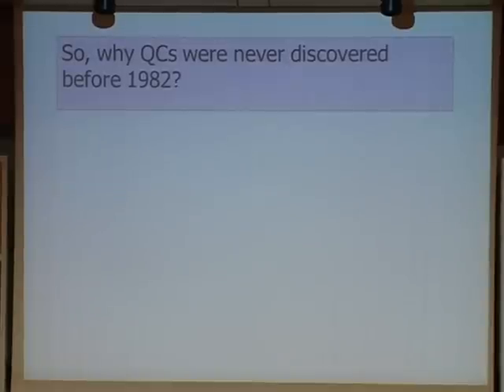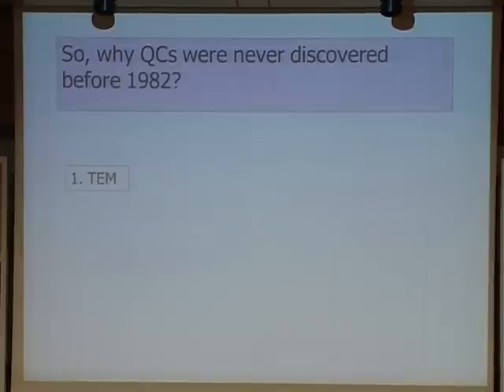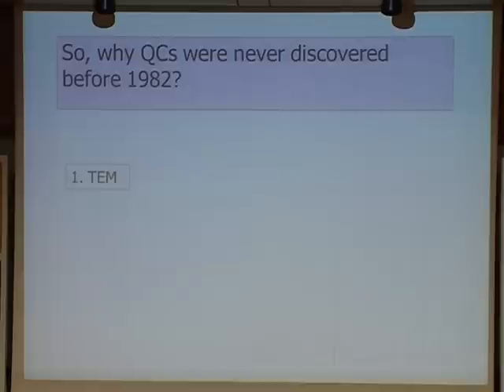Now let me give you my answer. You may have other answers. From now on, it's speculation. I think the following. Number one, quasi-periodic materials had to be discovered by TEM, by transmission electron microscope. And this is because they were very small. If you do X-rays, you see rings and you lose the rotation symmetry. You have to have a single crystal diffraction pattern to see the rotation symmetry. And only TEM could do that.